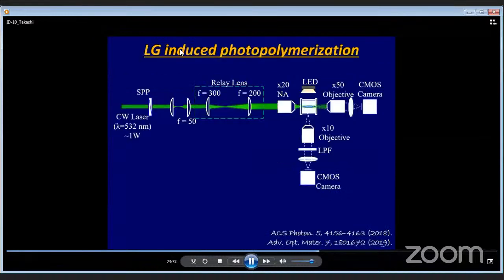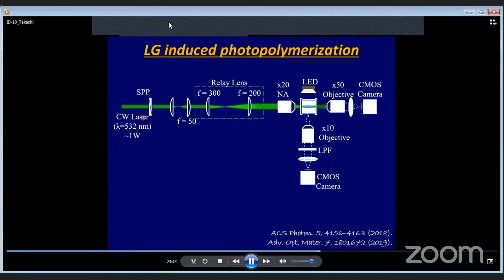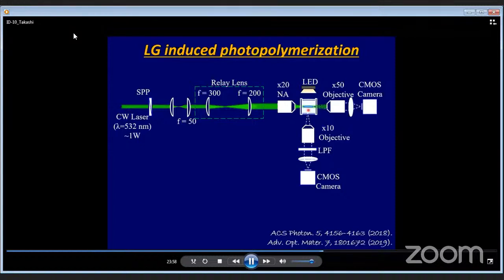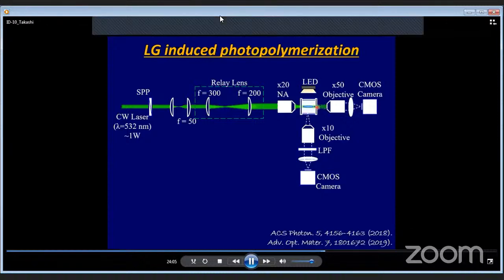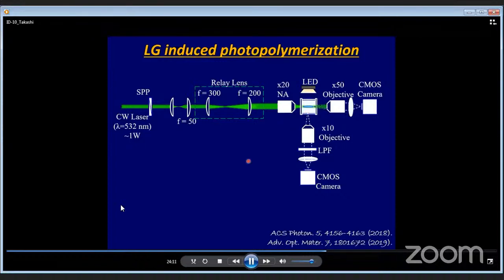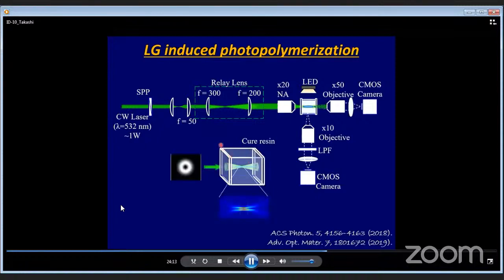Experimental setup is quite simple. We create optical vortex by using spiral phase plates. The laser wavelength is 532 nanometer, a green laser. Laser power is about 1 watt. The created optical vortex is focused inside the cell, including the liquid phase regime. Transmitted light is observed by a CCD camera, and the photopolymerization effect is also observed by a CCD camera from side view. Thickness of the regime is about 1 centimeter typically.